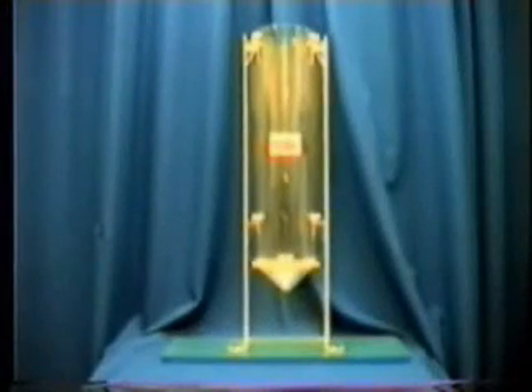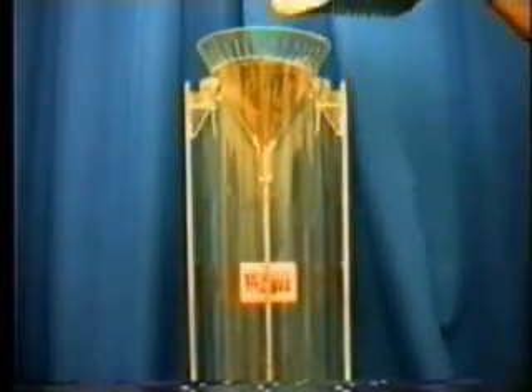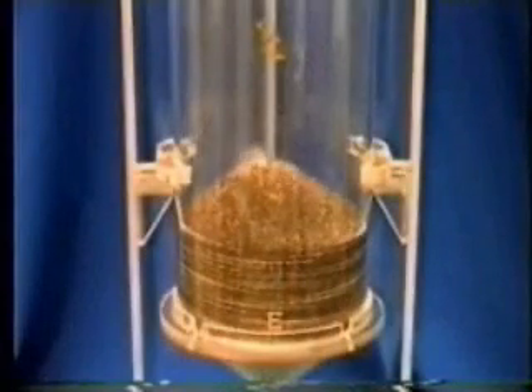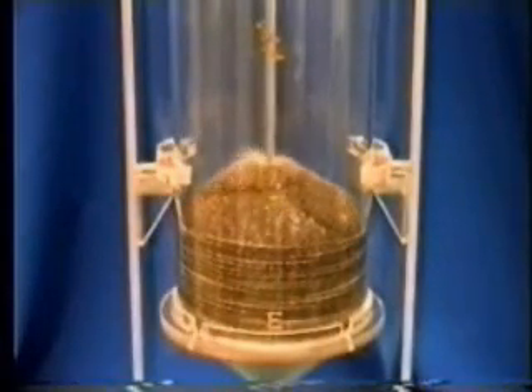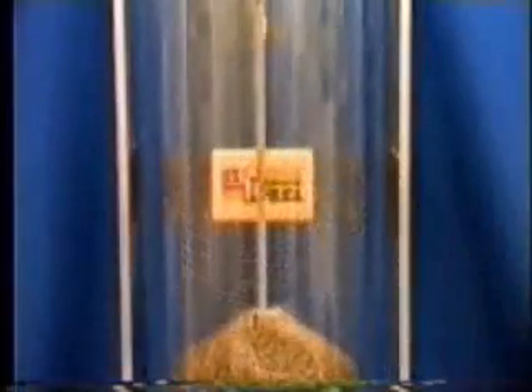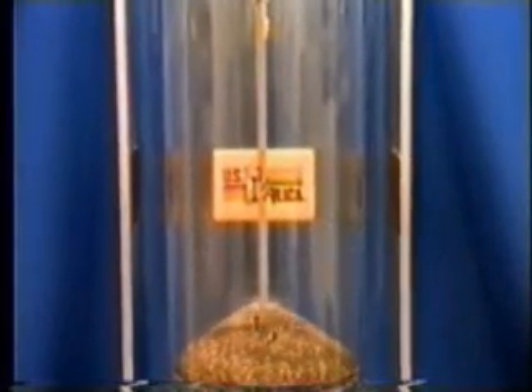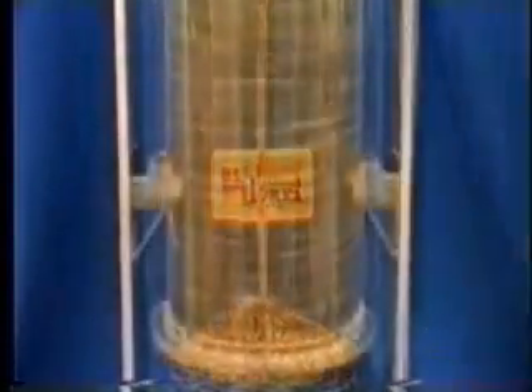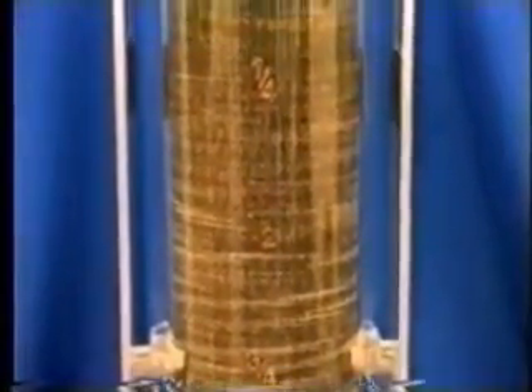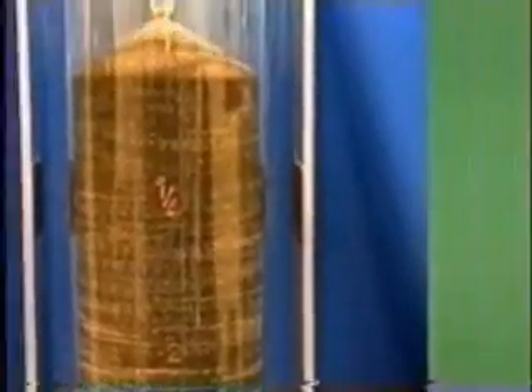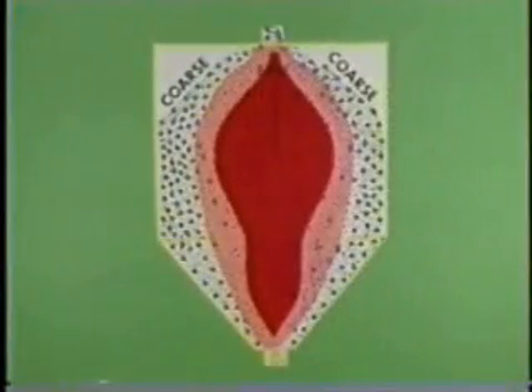For the next test, a miniature bin has been fabricated from plexiglass to simulate a foundry sand bin with a common top fill and bottom cone discharge. The bin has no anti-segregation devices. A sufficient quantity of the mixed sand was introduced into the bin to duplicate the normal flow in the foundry. Again, the sand segregates immediately within the bin, the fine staying in the middle while the coarse rolls to the outside. The outside of the bin shows almost all black material or coarse sand, although only 40% of the total sand is black. This drawing illustrates what occurs within the bin.